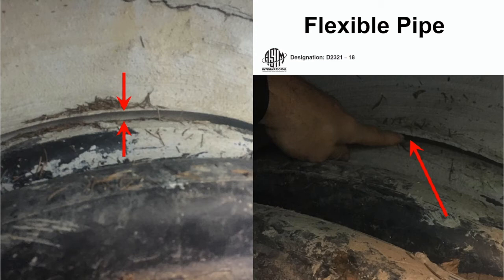The coefficient of thermal expansion for HDPE is about 13 times greater than that of concrete. Let's assume the pipe sat in the sun on a nice warm summer day and reached a temperature of about 110 degrees. After installation, a soil temperature of 50 degrees would be reasonable. If we assume this 60-degree temperature differential, the 36-inch diameter pipe would reduce by about 5/16 of an inch.